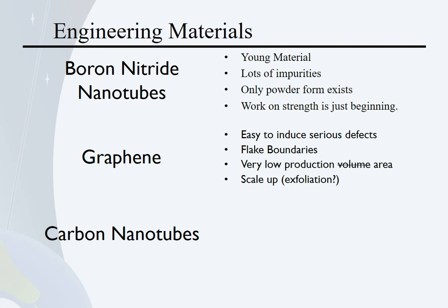As a matter of fact, that's not only the best method, that's the primary method of making large flakes of graphene these days. This does not scale well, because even as you increase the surface area to be square meters, hundreds of square meters, your thickness is still one atom. It takes a lot of square meters to get up to kilograms or even tons when you're starting with one atom thick. The best approach for scale-up really does require new production methods.